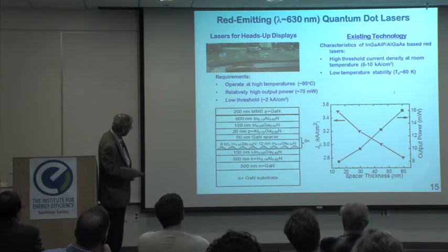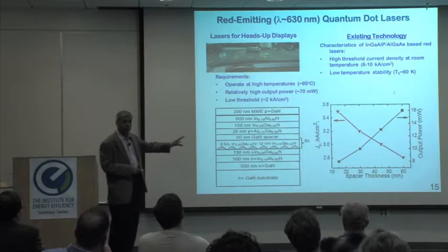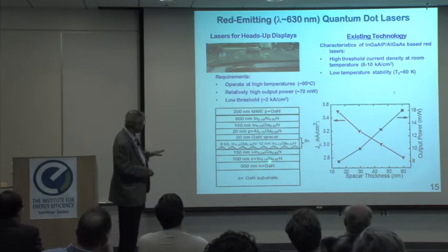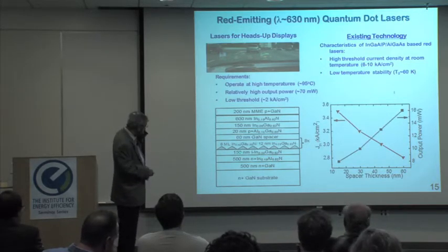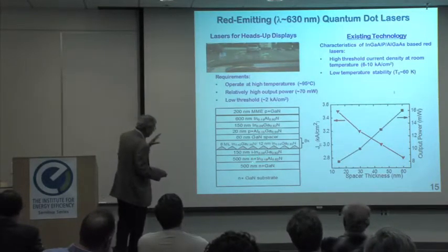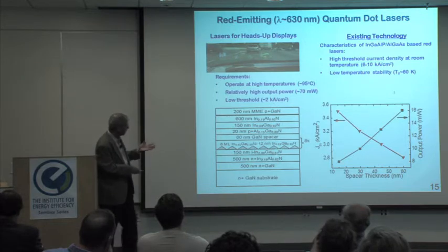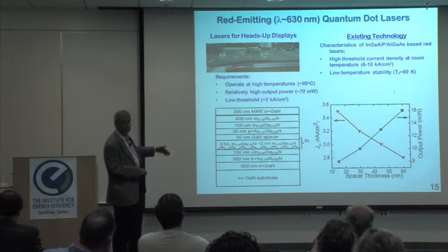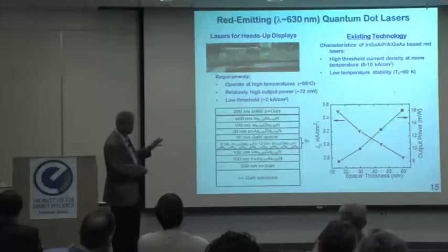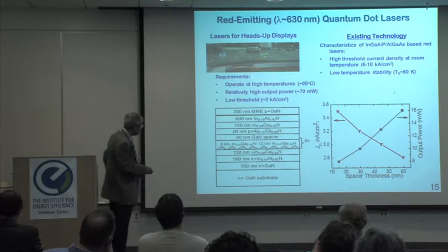We use indium aluminum nitride cladding, 18% indium, and that's about equivalent in band gap to the offset that we get with about 46% AlGaN, and 46% AlGaN is full of strain. So this is lattice matched, and growing this is very tricky. You have to grow it at a low enough temperature that the indium doesn't go flying, but high enough that the aluminum has some chance to move around and get incorporated. So we found a temperature of about 490 in these structures is good.